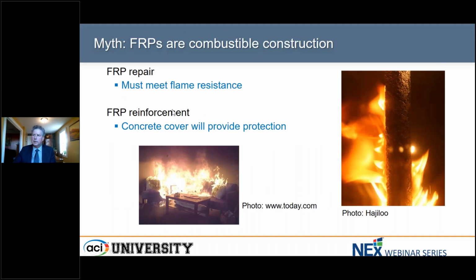So the first thing is that it's combustible construction. Well, really it's not. For FRP repair, particularly on reinforced concrete structures, the reinforced concrete itself is not combustible, and you're generally only putting a small amount of FRP on it for repair. But what you do need to do is provide some flame resistance so it doesn't burn immediately, but it doesn't change the main characteristic of the structure itself, and it certainly doesn't make it combustible construction. For internal reinforcement, it is inside the concrete by definition, and so the concrete cover will provide the protection and prevent the type of burning that we're seeing over here.